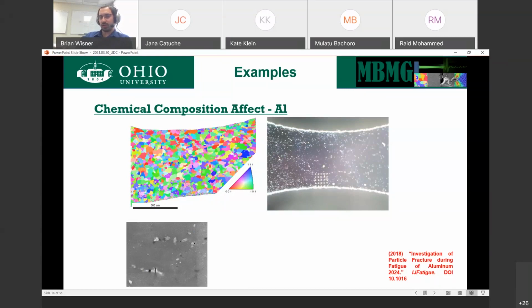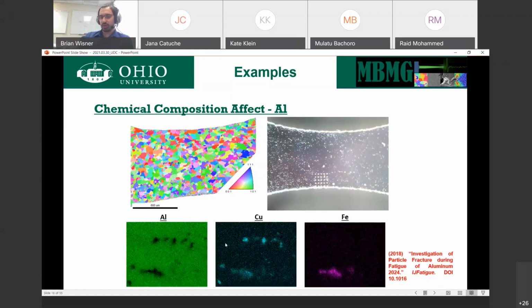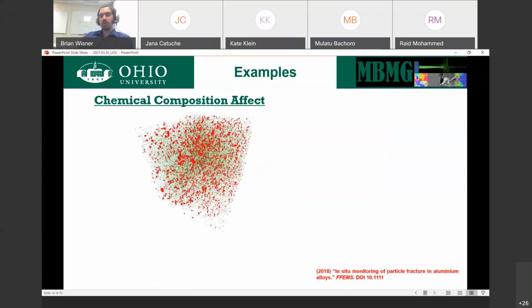So this particular alloy is aluminum 2024, precipitate hardened, which has larger particles that form during the process itself. These larger particles are damage nucleation zones, things we need to be aware of. Just so you're aware, we did validate what each of these particles is made of, and there's a reason for that. We also went through and characterized what the structure looked like to begin with, just so you have an idea.